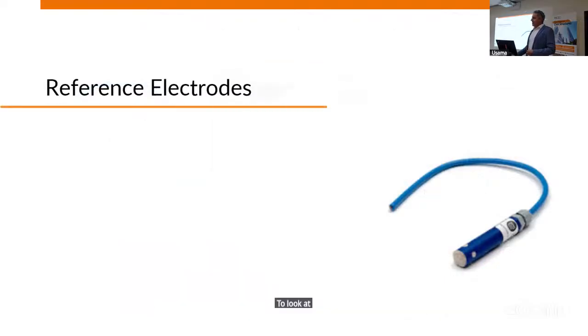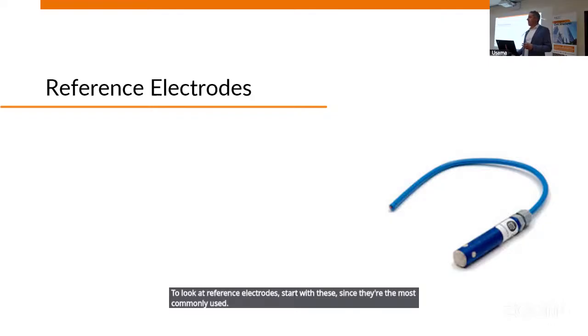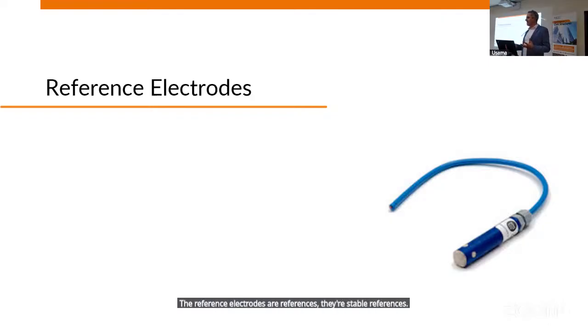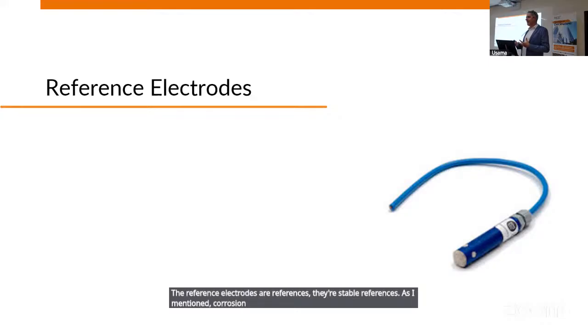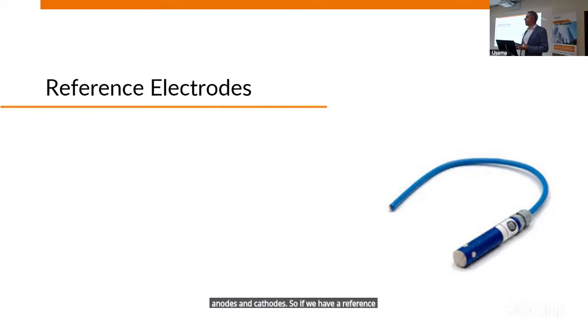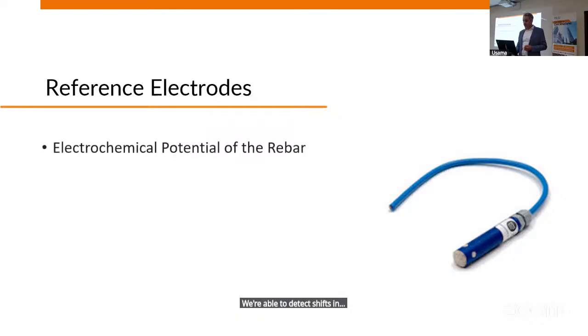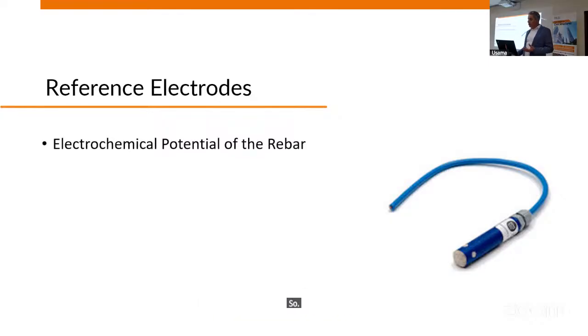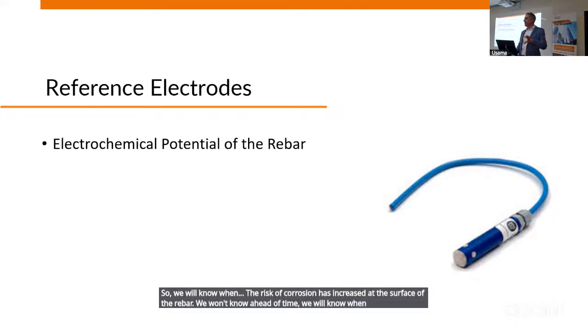To look at reference electrodes, start with these since they're the most commonly used. Reference electrodes are references. They're stable references. As I mentioned, with corrosion we have a dynamic nature of anodes and cathodes. So if we have a reference to benchmark, we're able to detect shifts in potentials on the steel. So what we're monitoring is the electrochemical potential of the rebar. So we will know when the risk of corrosion has increased at the surface of the rebar. We won't know ahead of time. We will know when something is happening at the surface of the rebar.